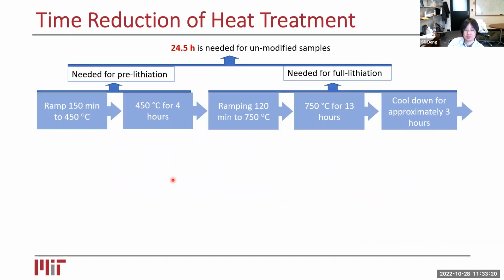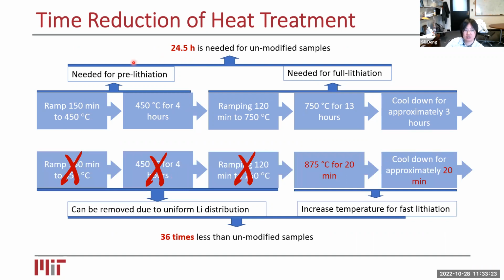And here is the summary of things, right? In the traditional method, after we get the material, we need to do this annealing process. The annealing takes 13 hours in industry. And also the material is so sensitive to temperature that you cannot just open the oven and put the particles in. You need to ramp it up from low temperature gradually. So the entire time needed in industry is more than a day, or roughly a day.